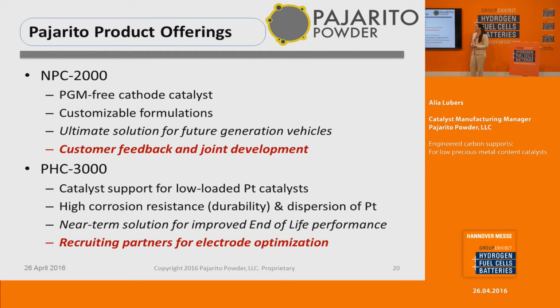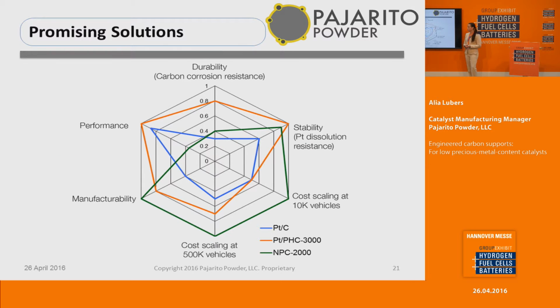So that was a summary of our engineered carbon support, our PHC 3000 line. We also produce catalysts that are completely platinum-free, if that is what you're going for. So in comparing platinum on carbon catalysts that have a lot of platinum, which is what we see these days, what we are trying to achieve is similar performances, but really driving this cost down at scale. And how we strive to achieve that is by reducing the amount of platinum that is needed by having a robust and even slightly catalytic carbon support, or eliminating platinum completely.